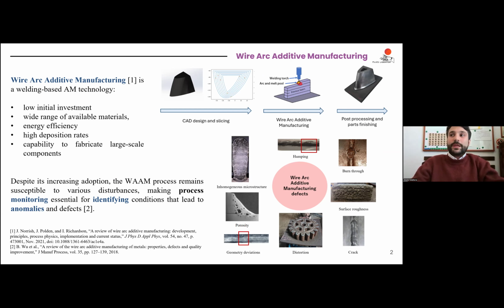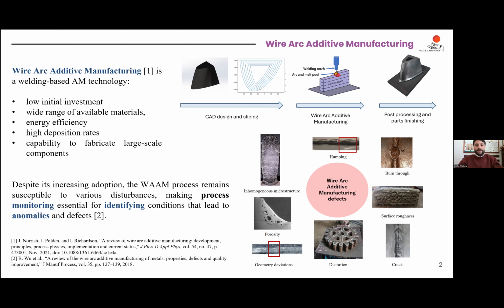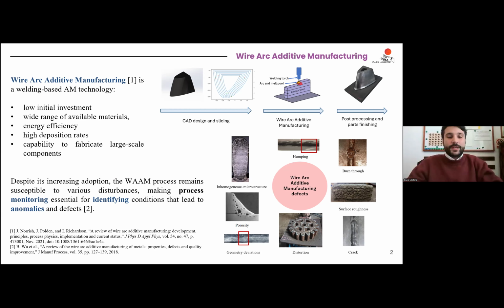And also because you are not limited by the envelope of the powder based machine that you are using for additive manufacturing with powders. The only problem is that it's really prone to get a lot of defects inside the process. And not speaking only about porosity, that is something common also in laser based or powder based, let me say, additive manufacturing. But here you're going to get really rough surface. You can get easily humping problems, geometry deviation with respect to the path, distortion, that are going to make your part not useful to be used in a real use case scenario.